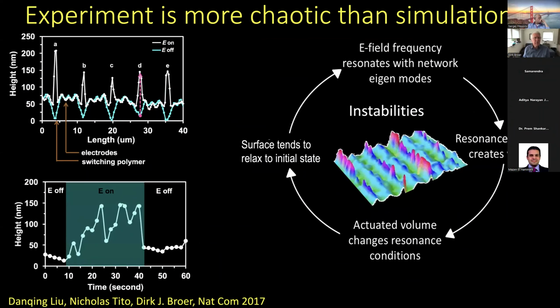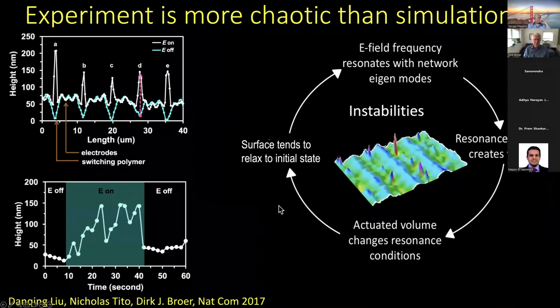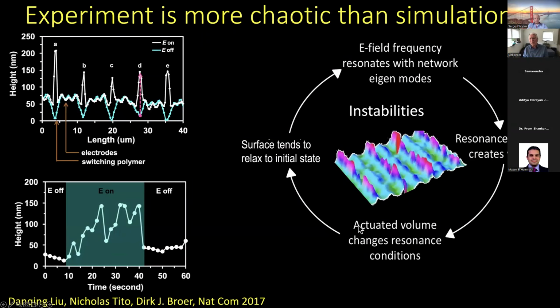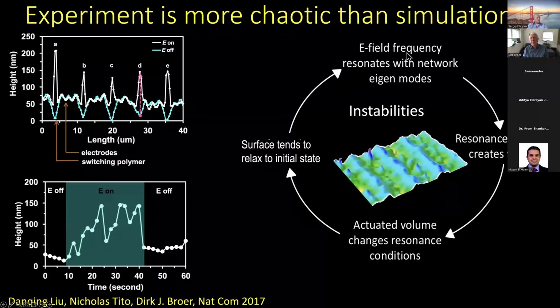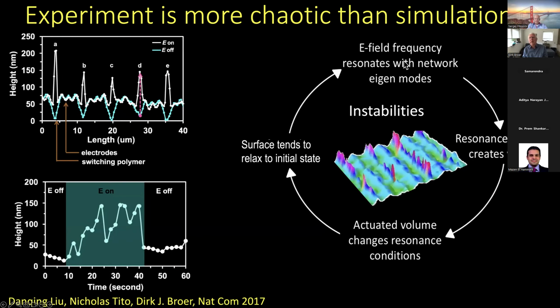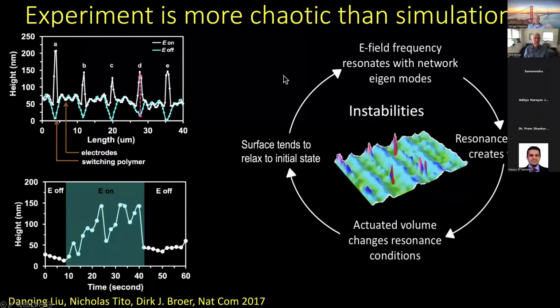The deformation is, however, rather unstable, so you can see here. So it's not a simple expansion, and if you switch off the field, it goes away. So we had to find some explanation for that, and the explanation that we came up with, it is not a proven explanation yet, it's just a postulation, is that the electrical field resonates with the eigenmodes of the network. Then you have resonance. That is the moment that you start creating the free volume. But as soon as you have the volume created, the resonance conditions are changing, and the system falls back to its initial state. But then it starts becoming actuated again. So this is a process that is continuously repeating itself.